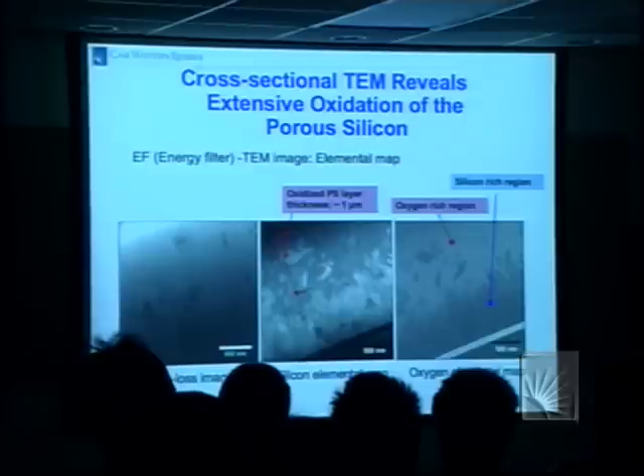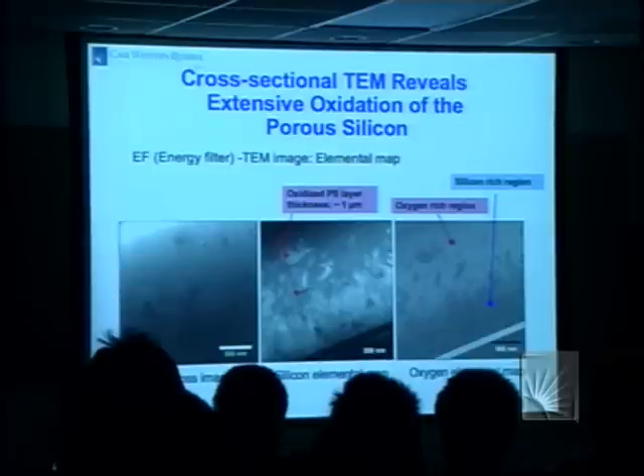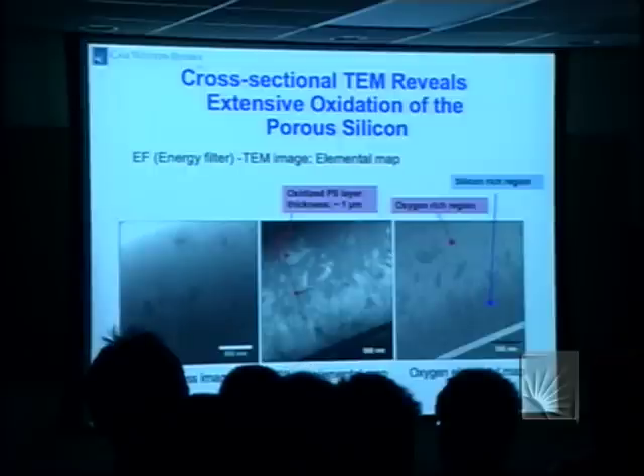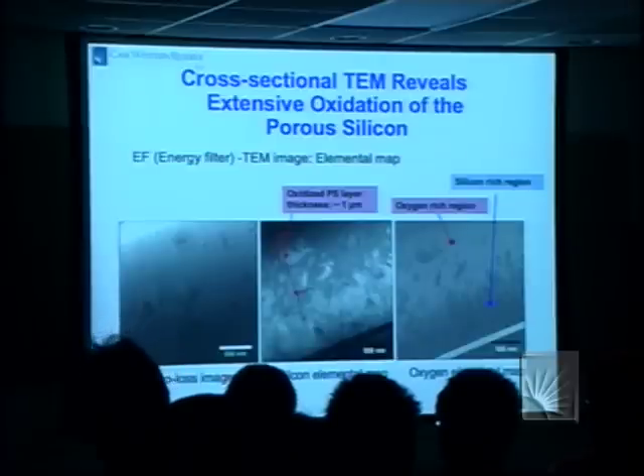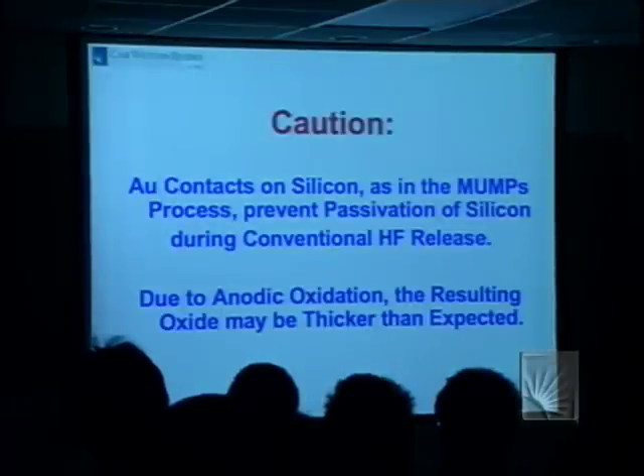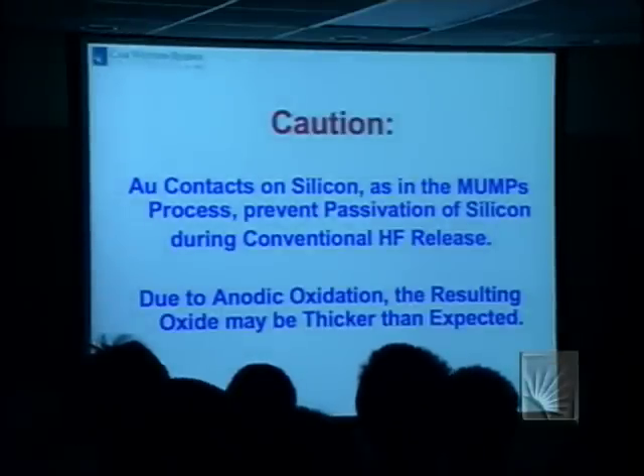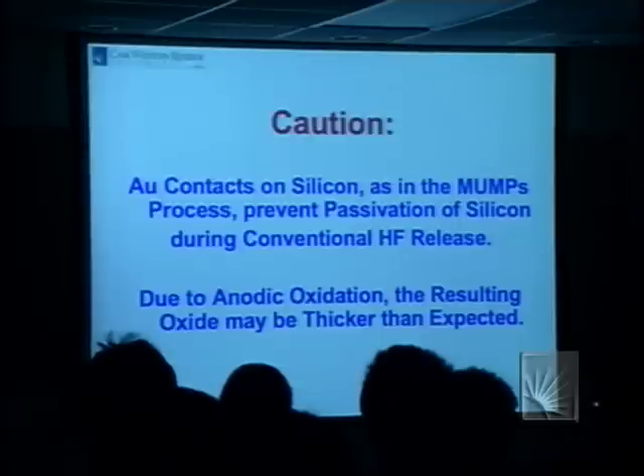What's happening is that the release step causes a porous silicon to be formed, and it does form a thin native oxide, but there's so much surface area of porous silicon that you get something which looks like a silica, non-passivating silicon, and appears to grow, there's so much porous silicon present. So, caution, gold contacts may be dangerous to the health of your device.